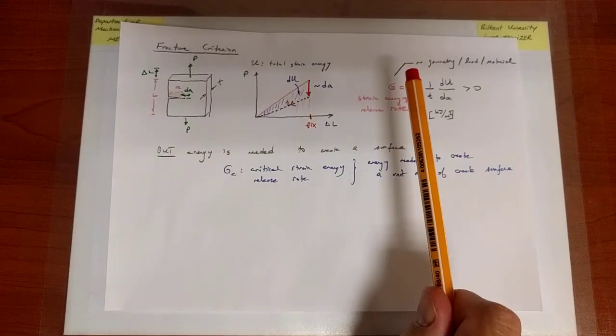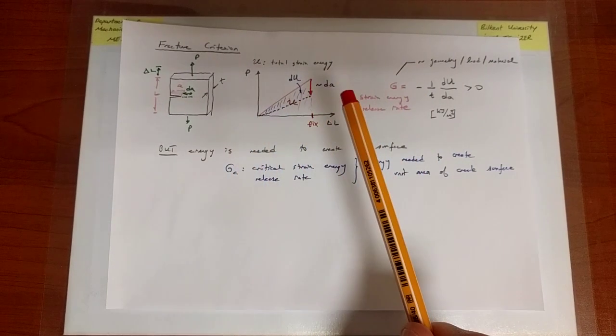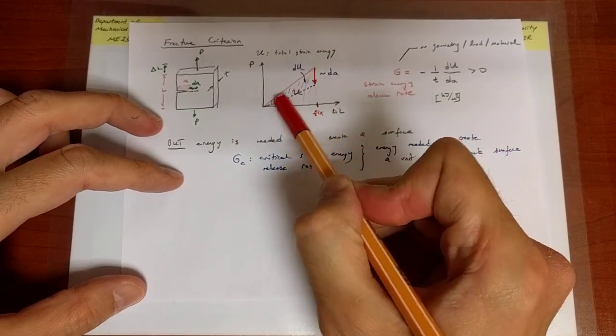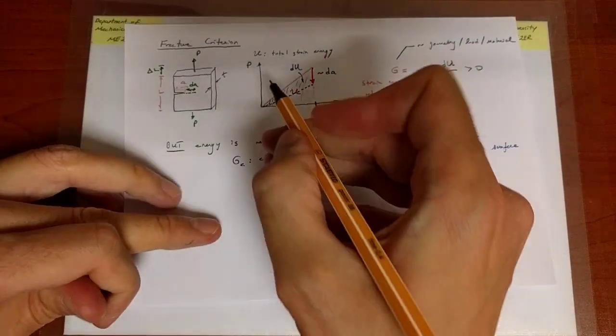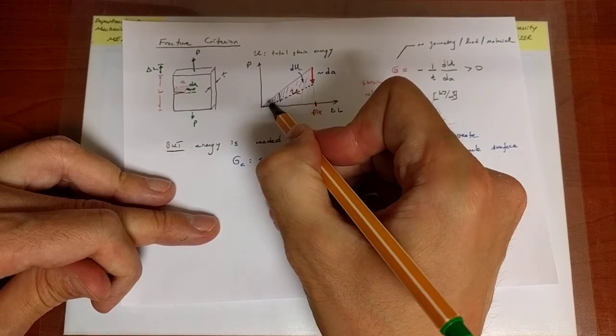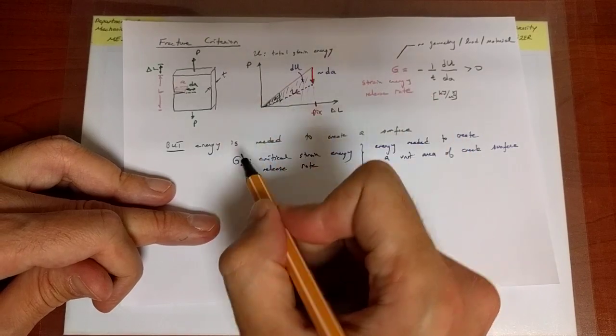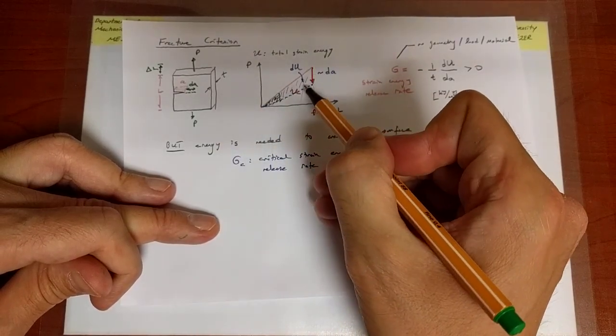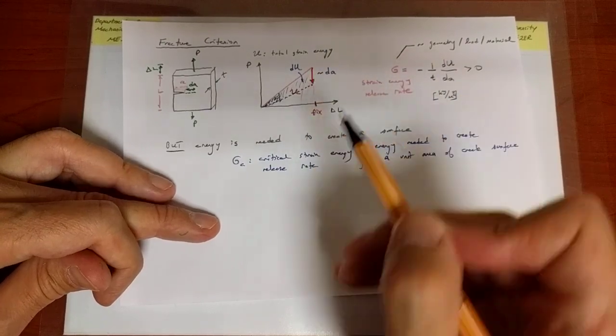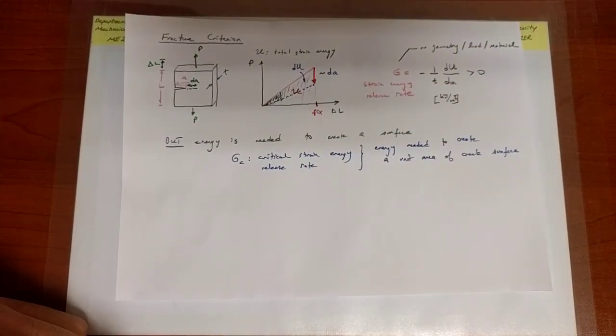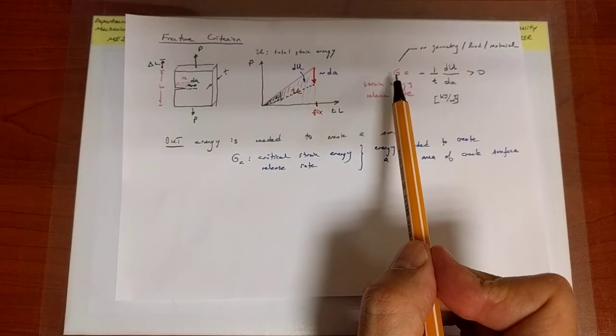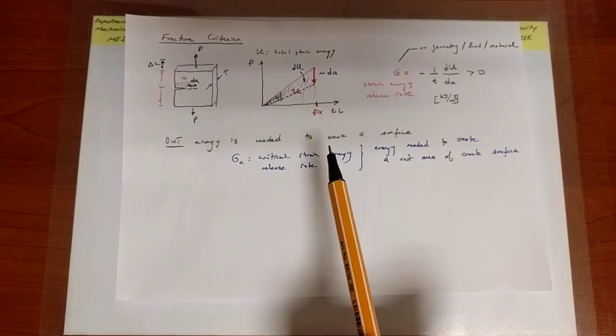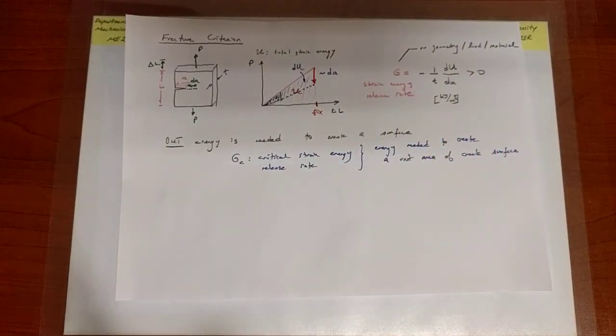What you should notice is that G is something that will continuously grow, right? Because the amount of energy that is released at any stage is this area. If I had unloaded at this stage, the amount of energy that was stored would be just this green portion. If I load more and more, the amount of energy that is available when the crack propagates by a certain amount is going to be larger and larger in an actual loading scenario. So G, as the load increases, will start increasing. And on the other hand, physically, what is needed is GC for the crack to propagate. So think about that question for a second.